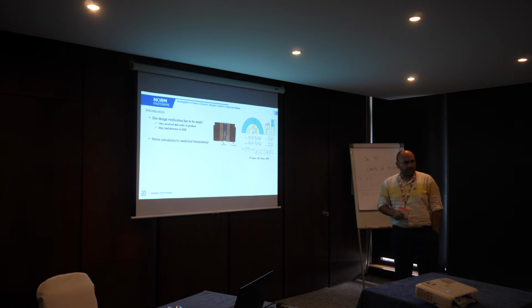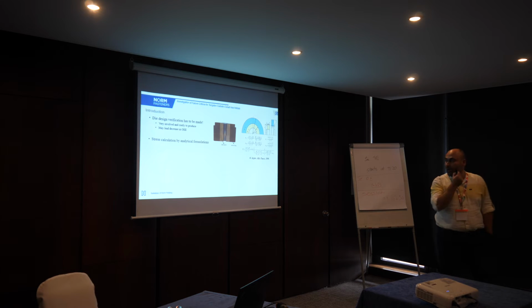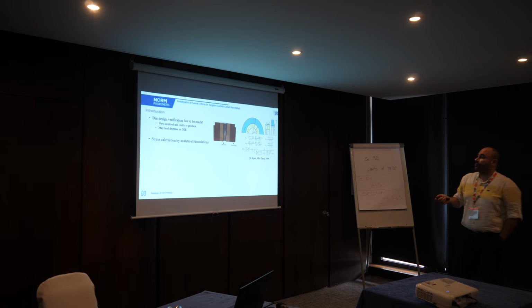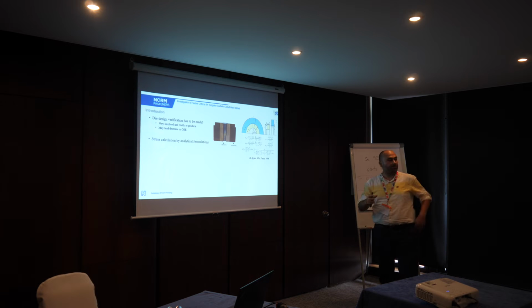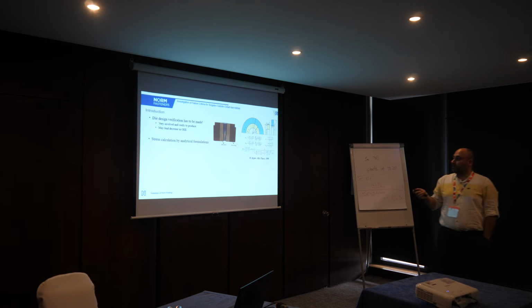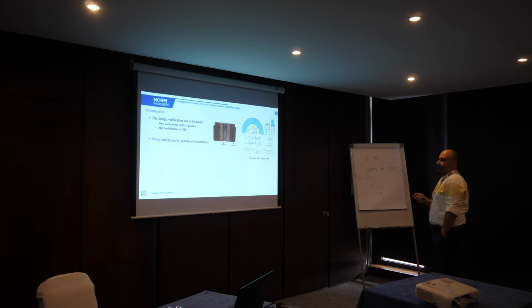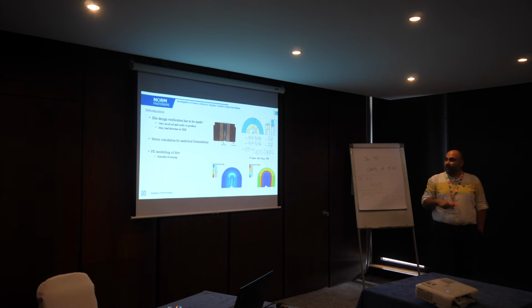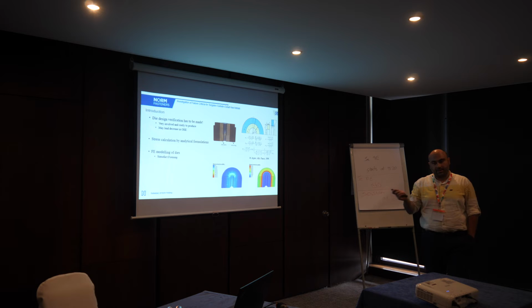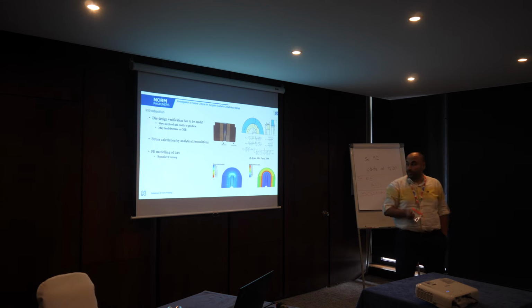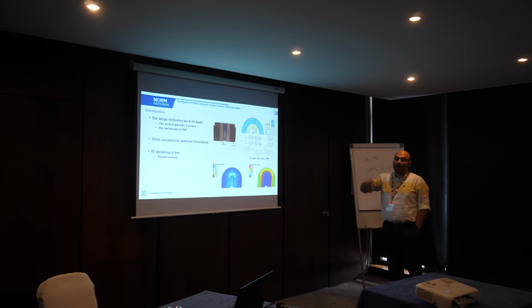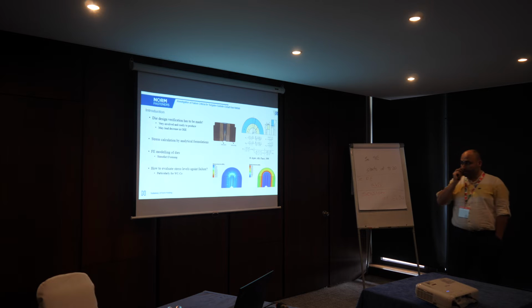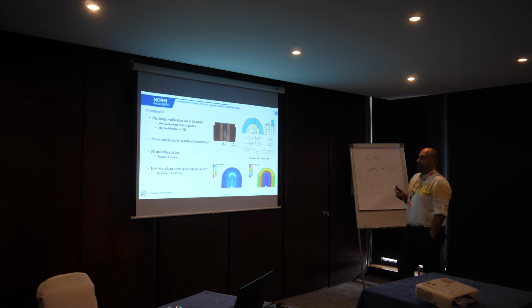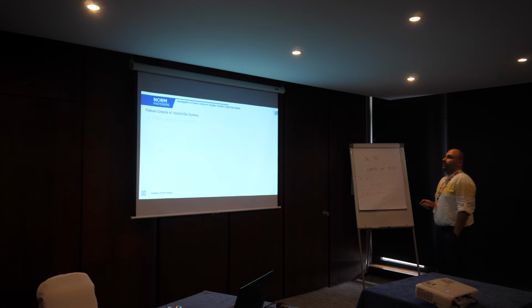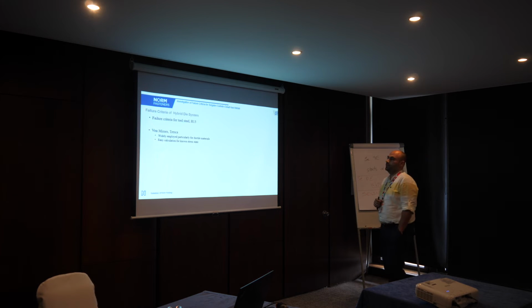Thanks to our former colleague Mert Aygen, in his master thesis, he found a way to calculate hoop stresses and radial stresses with this pre-stressing ring. So by analytical formulations, I can calculate stresses. I also have FE modeling, so I can get stresses for tungsten carbide cobalt and tool steel for this particular hybrid die. But the problem is how to evaluate stress levels against failure, particularly for tungsten carbide cobalt. Why? I'm coming to this topic.